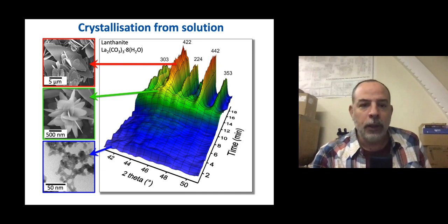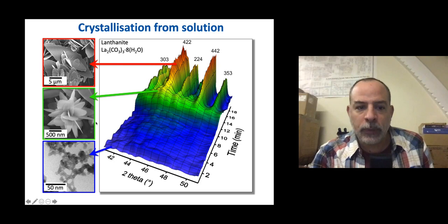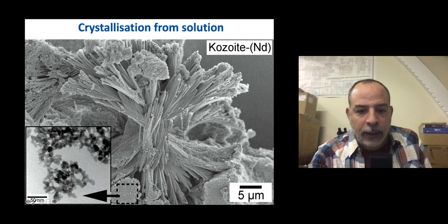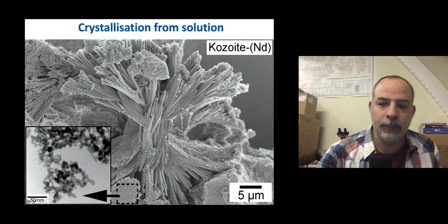From an amorphous phase, the mineral lanthanite forms at ambient temperature and crystallizes and grows. The same happens with other minerals — kozoite also forms from an amorphous phase. You can see the amorphous material as nanoparticles, with larger crystals forming by spherulitic growth. The lifetime of the amorphous phase is proportional to the mass of the rare earth element.